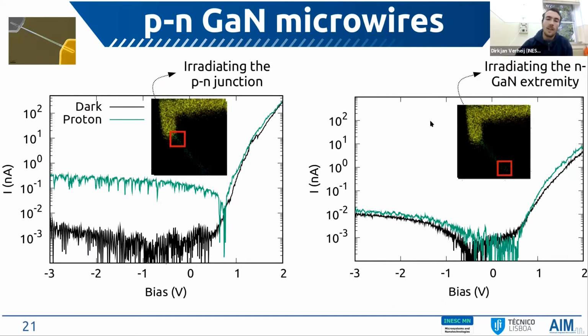Just as we did for the n-type microwires, we decided again to irradiate specific areas of the device, and in this case we have very different areas. At one side, we have the p-n junction, and at the other side, we are only irradiating the n gallium nitride, because, like I said before, the p-n junction is only located at the top part of the wire. We see that the results are completely different. When irradiating the p-n junction, we obtain a signal similar to the one measured with the UV light. When irradiating the n gallium nitride extremity, the ionocurrent response is almost negligible compared to the dark current.